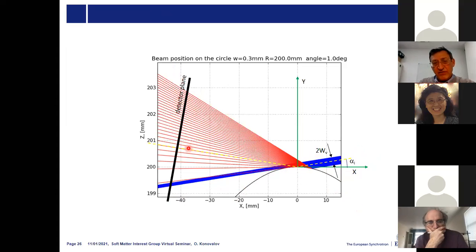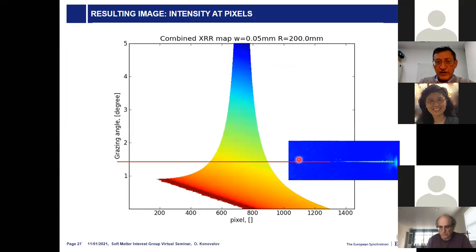So then if we find a technique to identify, on a given pixel, which part of the incident beam reflects from the surface, then we can normalize it, and then we can know what is the intensity which corresponds to this Q, because each ray now is reflected for a different Q vector. So then we succeeded in making this mathematics and were able to calculate in both directions, simulate data and go back from the experimental data.